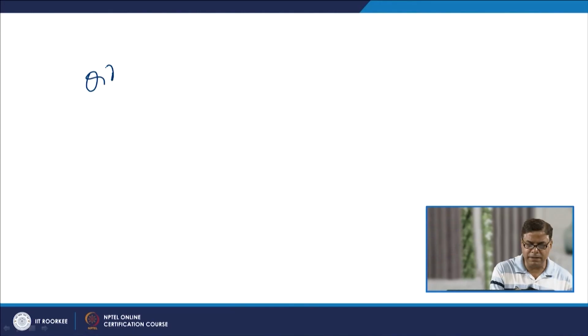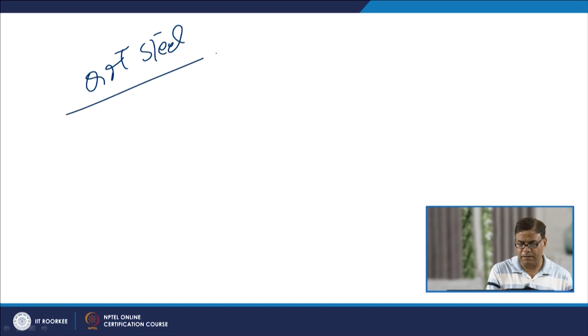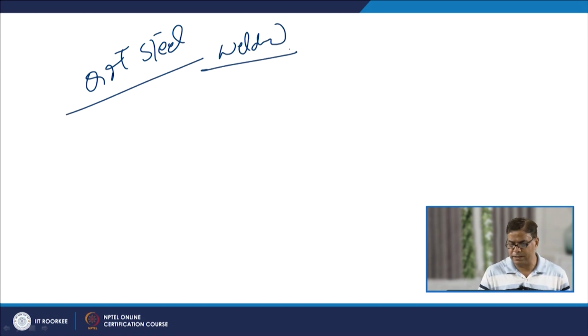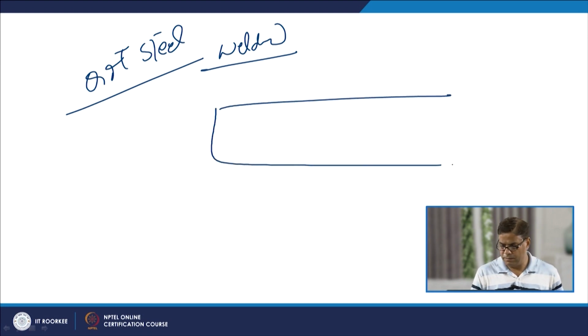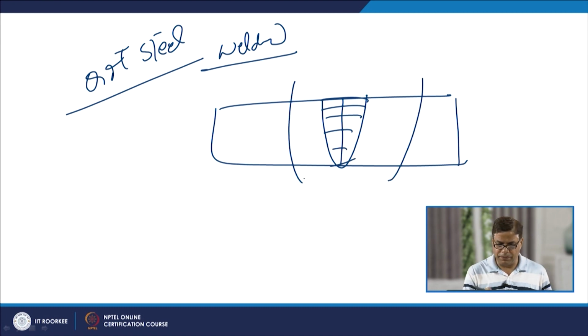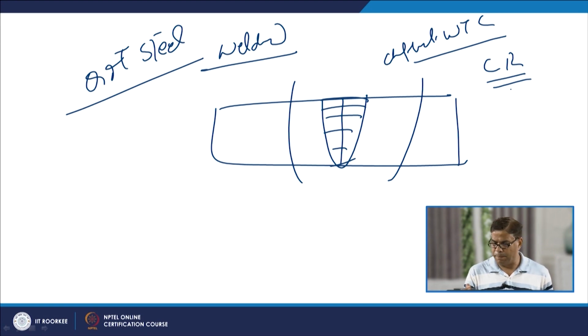Now, we have seen that when the Q&T steels are welded, the weld metal as well as the heat affected zone will be experiencing different weld thermal cycles in the different zones, and the cooling rate experienced in these cases is found sufficient for the formation of martensite as well as upper bainite, sometimes lower bainite and ferrite.